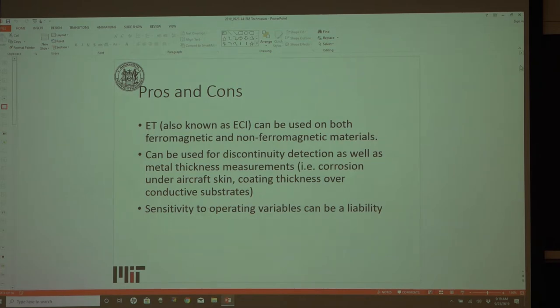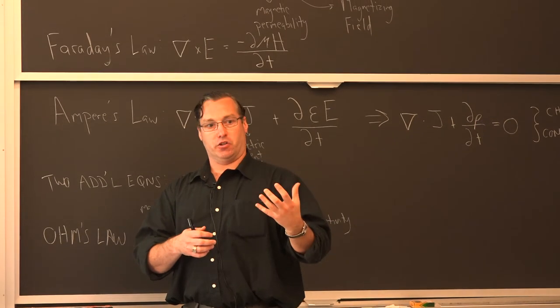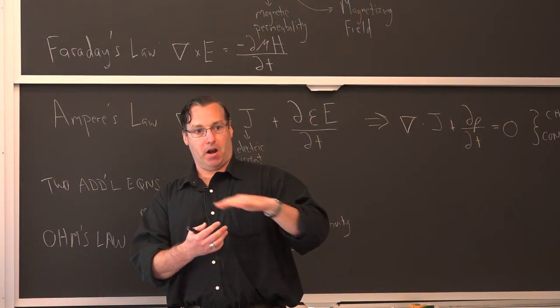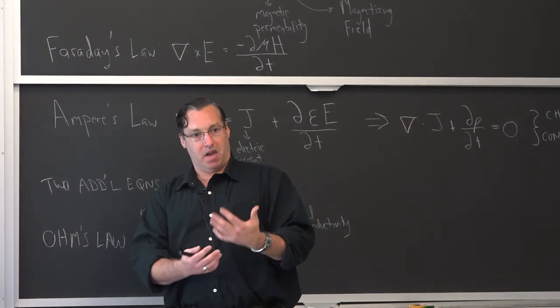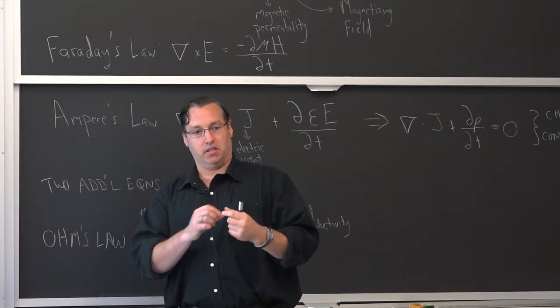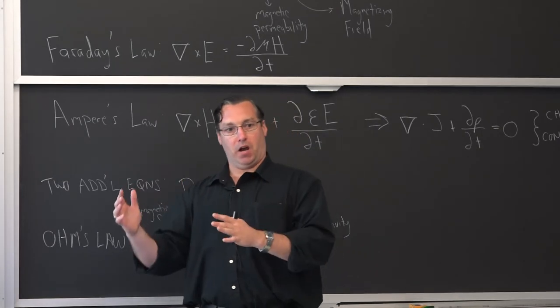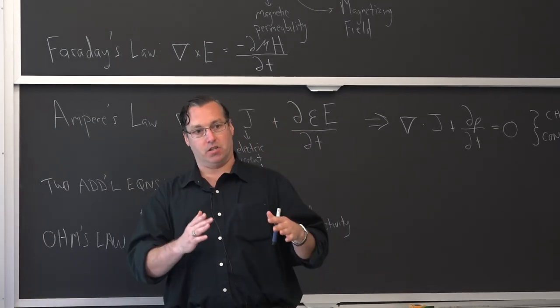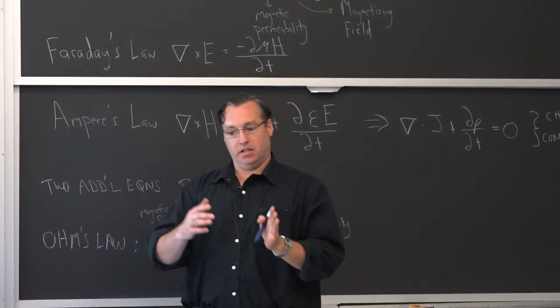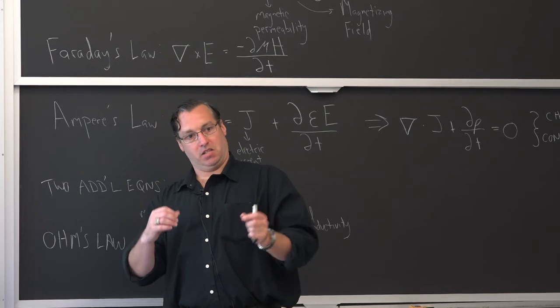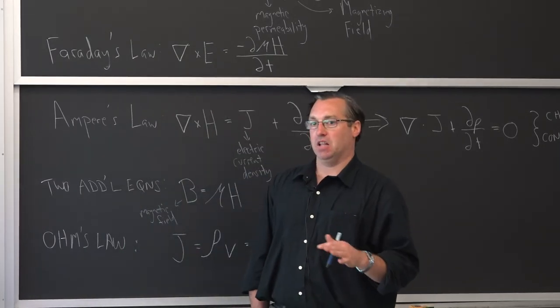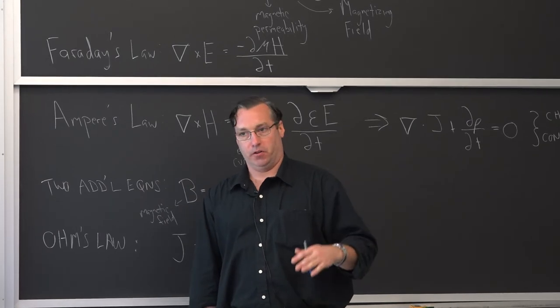Inspectors are sometimes sent to bridges to determine wall loss using eddy current techniques. When there's corrosion, they prep the surface, remove exfoliation or rust down to bare base metal, and then do the eddy current test to give you remaining wall thickness. That determines if a structural member needs to be repaired or can remain in service, and also gives guidelines on timetables for subsequent inspections based on percent wall loss — common for bridge inspections and structural components.